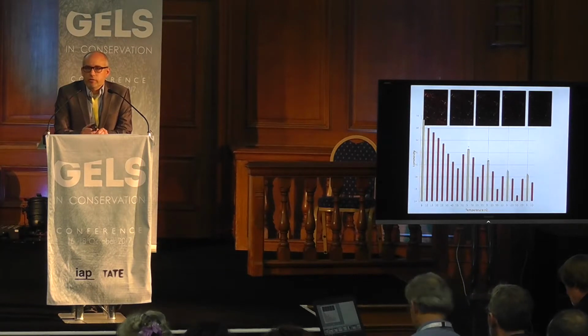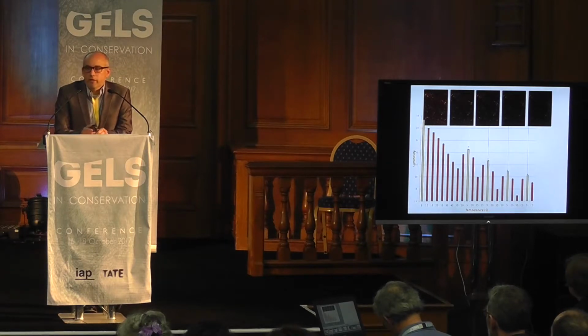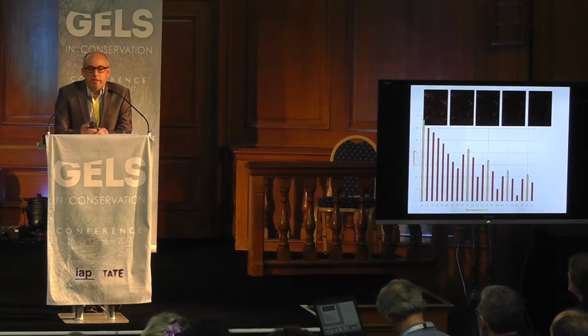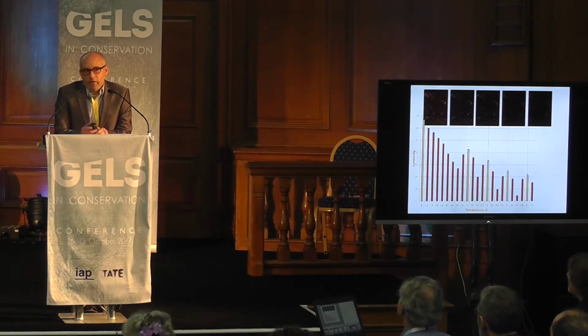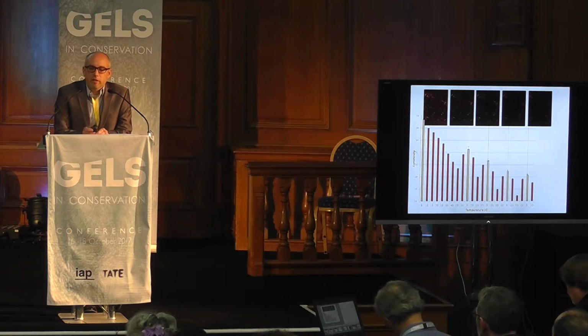Is it really the soiling mechanism in these paint bodies? Could it be triboelectric? Could it be that they're inherently soft? But this was one of those moments where we saw it move and we saw the soil move. And what's peculiar about this is we can bring it back out. As we decrease the temperature, we can bring those soils back out to the surface. But you'll notice, just over the course of a day here cycling, we can't bring them fully out. So the luminosity at the start of the day versus the luminosity at the end of the day is much less, which means we've moved soils irreversibly beneath that paint film. And that was some evidence that this could be the soiling mechanism in driving these soils into these paint films.